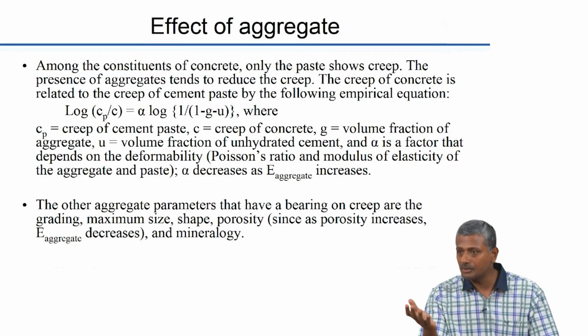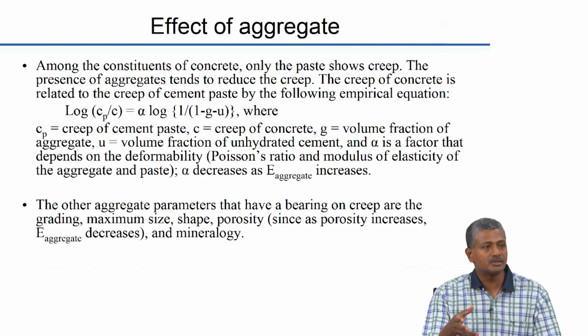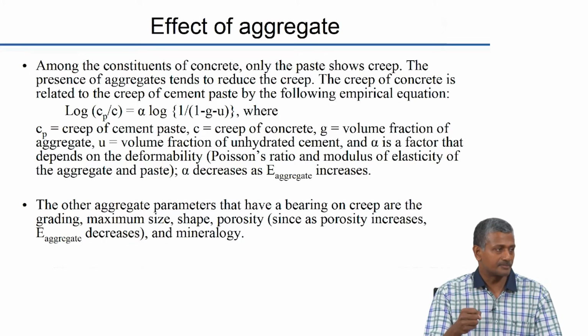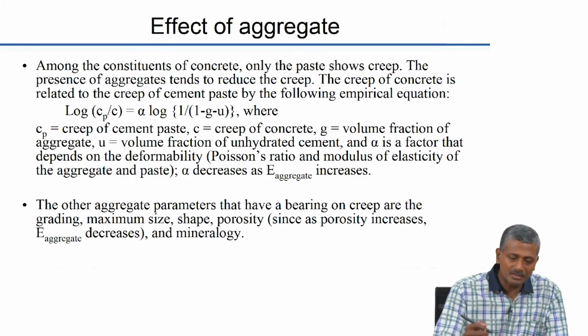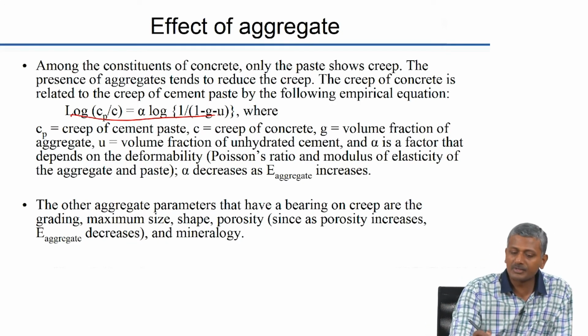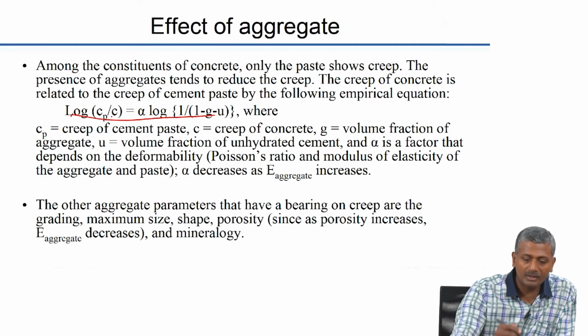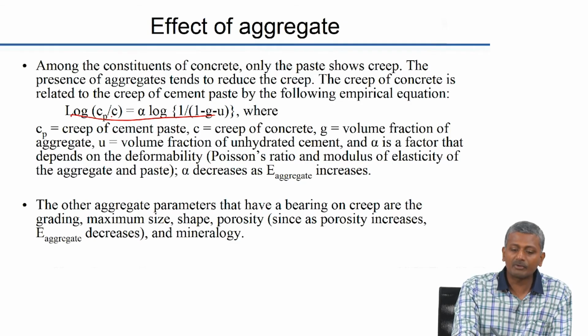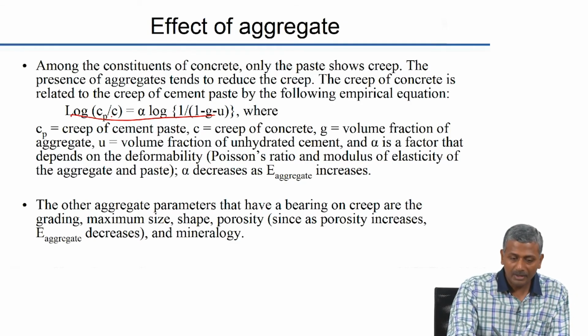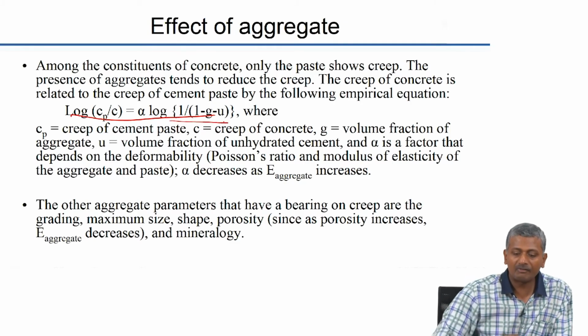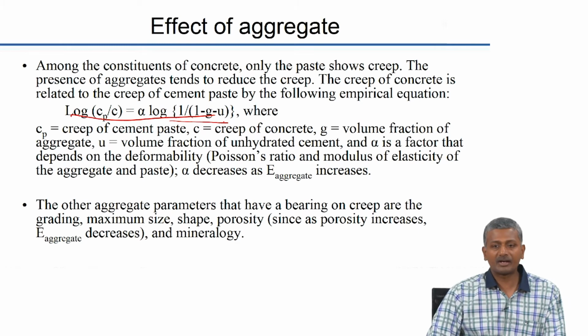And this exactly shows why we want to move towards the particle packing based mix design systems, where we are able to maximize the extent of the granular component and minimize the amount of paste in the system. Okay. So, again this is just a relationship proposed based on some research studies, where a logarithm is taken of the component on the left, that is creep of cement paste divided by creep of concrete, that is given by a function of the volumetric fraction of the aggregate.